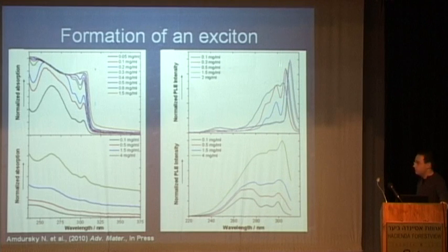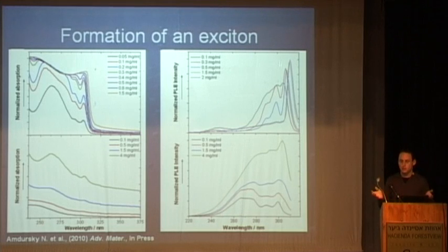characteristic that we found is by following the photoluminescence excitation of the structures. The photoluminescence excitation is basically like the absorption spectrum, but I detect the photoluminescence at a certain point and just excite the molecules at different wavelengths. So if we start from the negative control, we can see no matter the concentration, the photoluminescence excitation is broad, which is quite usual to organic molecules, and not only organic molecules, the photoluminescence excitation is usually broad.